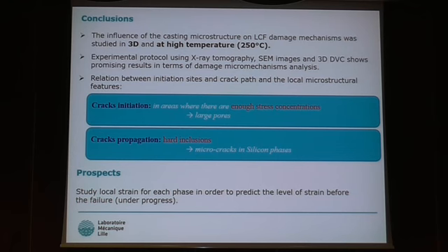So to conclude this work, in this study we can understand the influence of the microstructure on low cycle fatigue, the damage mechanisms in 3D at high temperature. The X-ray tomography images allow us to understand the damage mechanism and also to characterize the material in 3D. And digital volume correlation helps to understand the relation between initiation site, crack paths, and local microstructure features. So we can say that the crack initiation is porosity driven, in the area where there is enough strain concentration, while the crack propagation is along hard inclusions, and in this case above all in silicon phases.